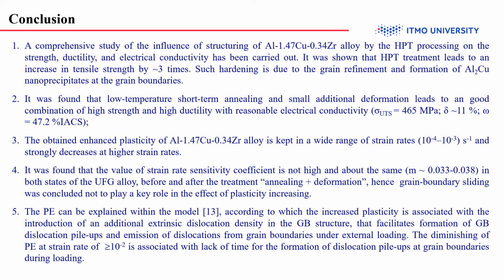The obtained enhanced plasticity of the aluminum copper zirconium alloy is kept in a wide range of strain rates and strongly decreases at higher strain rates. It was found that the value of the strain rate sensitivity coefficient is not high and about the same in both states of the UFG alloys, before and after the annealing plus deformation treatment. Hence, grain boundary sliding was concluded not to play a key role in the effect of plasticity increasing.